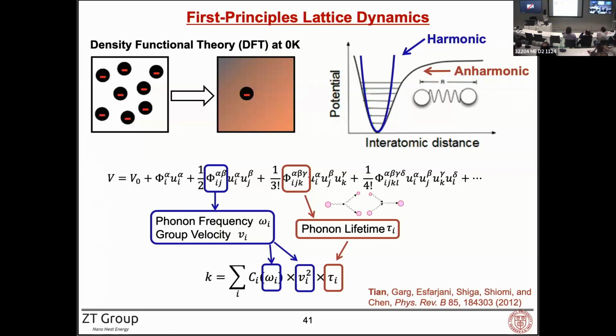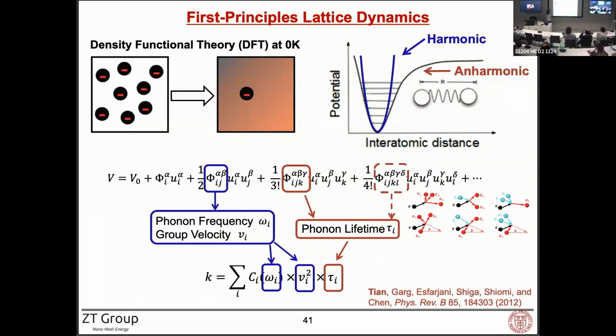But now we probably need to consider a little bit more in this case, because we are talking about the high temperature behavior, then the 4 phonon scattering can become important, and that would affect the overall lifetime. And the third order and the fourth order force constants can also renormalize the frequency and shift the frequency obtained from the harmonic calculation.